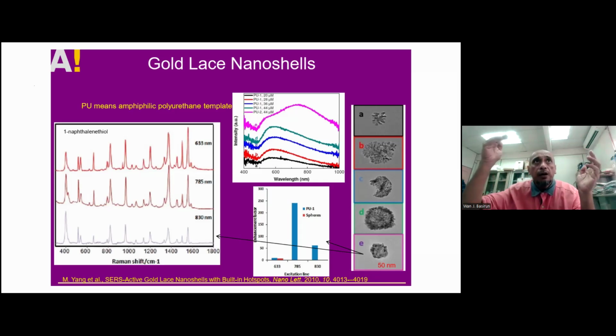So whenever you have chemical changes in the biological sample that induce structural or morphological changes, then you can use this technique to analyze. But if the chemical state is still intact, then most probably you cannot observe anything, because this technique, just like other spectroscopic techniques, detects changes in the chemistry, in the bonding or in the functional group. Like when you have ferrum bonded with porphyrin, you won't get the same spectrum as ferrum bonded with oxygen. After oxidation you get ferrum oxide, and that is not the same as the ferrum bonded with the porphyrin in the hemoglobin of the blood. So that is one.